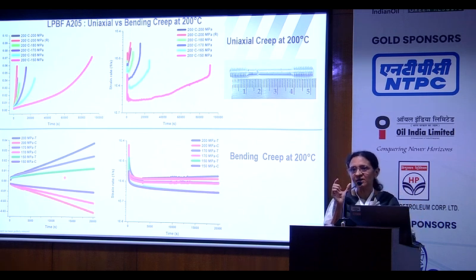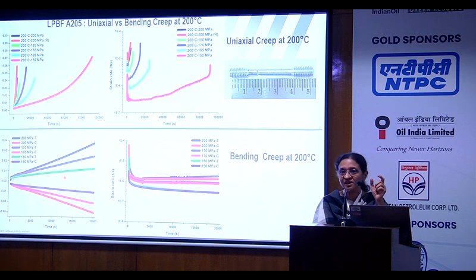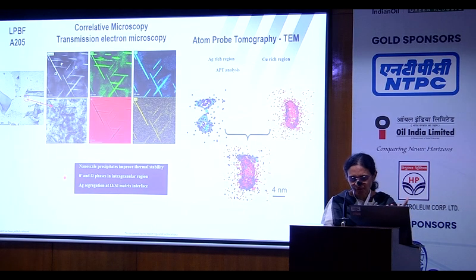Everything in one little bar. If you want, you can repeat it once more, but imagine taking a tiny specimen, not more than an inch long and 2 millimeters in cross section, and you're getting the entire creep curves. And then of course, since I'm an electron microscopist, we can't not look at what is the mechanism of creep.